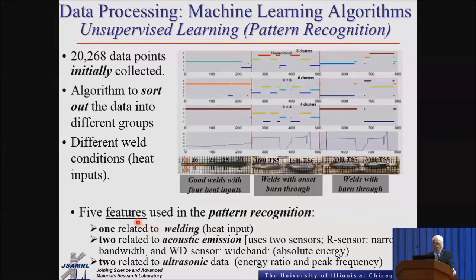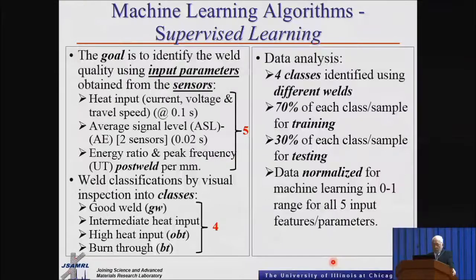The features that we used for the pattern recognition: one was the welding heat input; two were related to the acoustic emission. We had two sensors, one a narrow bandwidth and the other a wide band sensor. Also, there were two sensors in the case of the ultrasonic data, to use the energy ratio and peak frequency. So this pretty much summarizes what we call supervised learning.